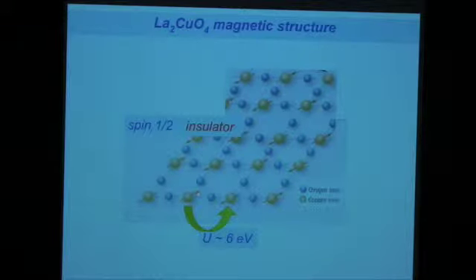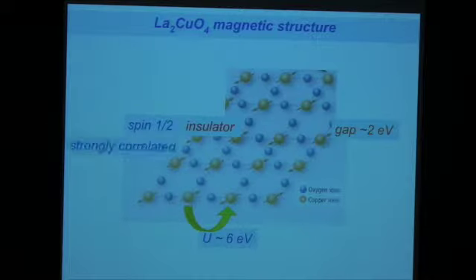Because if an electron, or in this case a hole, moves from one copper site to another copper site, this becomes occupied by two holes, and they repel each other severely by a Hubbard U, which is in the order of 6 electron volts or so. Okay, so the electrons are not able to move due to this large energy penalty. The system becomes insulating, therefore, and a gap opens up of about 2 electron volts. Okay, it's a strongly correlated antiferromagnet.